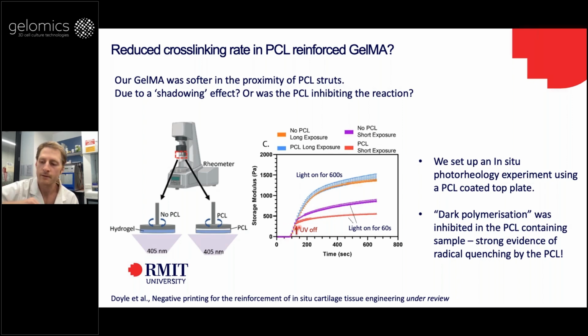So in that case, this is a free radical polymerization reaction. The radicals are live, they're moving through the gel. The polymerization continues for quite a long time, even after the light is turned off. But the reaction stops a lot faster when you have a PCL plate rather than when you have just a normal steel plate. And so this supports the idea that the PCL is actually quenching some of those radicals and then slowing down the reaction.